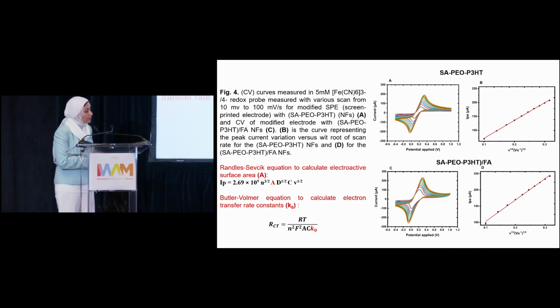Here we examined the effect of different scan rates in the range of 10 to 100 millivolts per second on the intensity of peak current in both layers, the conducting nanofibers and after conjugation with folic acid. And the same, we obtained an increase in the peak current, and we made fitting and extracted the value of Ip, which is the peak current, against the square root of the scan rate. We obtained a linear relationship. This linear relationship confirmed that our electrochemical process is diffusion-controlled, which is highly recommended for our biosensor, and confirms enhancement of sensitivity.